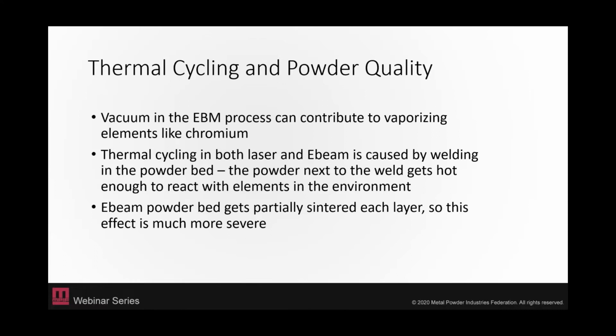So getting back to thermal cycling and diving in closer. I'm thinking most people know what happens to certain metals when they're melted in a vacuum, right? They vaporize. And one of the metals that is particularly susceptible to vaporization is chromium. So we know that some elements have high vapor pressures like chromium, and they can leach out at those high temperatures in a vacuum chamber like we have with the electron beam. Your stainless steels, your Inconels, and lots of alloys have chromium in them. And so that vacuum is not only an issue for your part chemistry, because you will see a change in that, but it's also the powder, it's what that powder leaves behind in the machine.